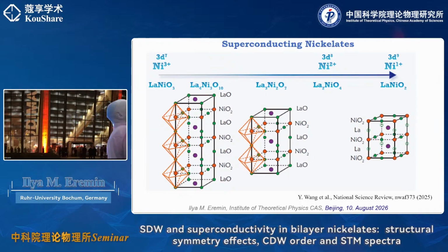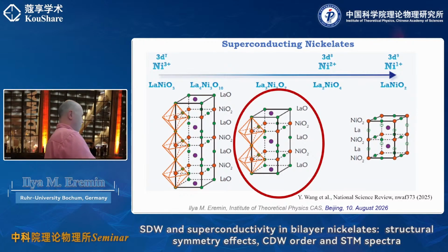And initially people were not expecting it to be a superconductor. And this is the system which you have. You have nickel oxide layers, which are connected by the apical oxygen. Okay. And 4310 is also very interesting. It also turns out meanwhile to be superconducting under pressure, but Tc is much lower and the pressure is much higher. So experimentally it is much more difficult to study, especially the superconducting phase here. There are a lot of studies and interesting magnetic phases, but in my talk I will primarily concentrate on analyzing only this system because of the time.